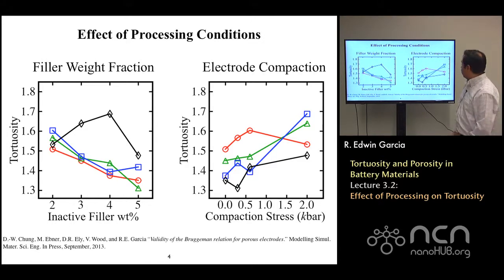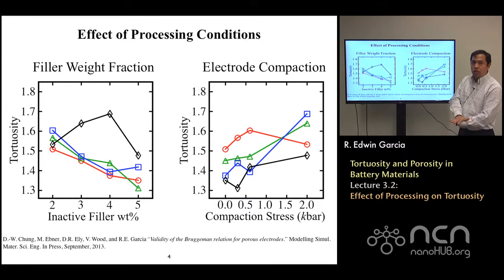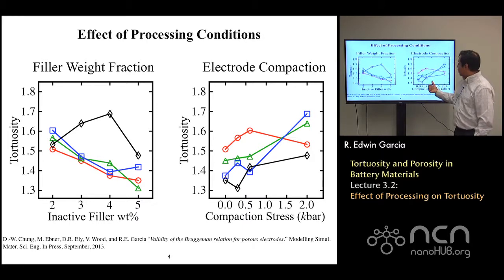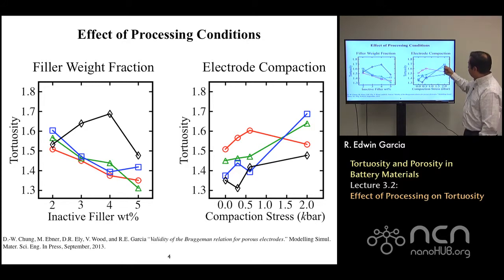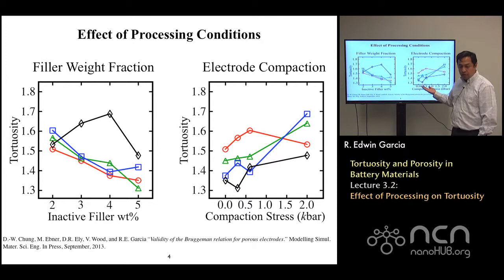If you see the same response as a function of compaction for a fixed amount of filler, they roughly follow the same trend. As you compact your electrode, particles get closer together, making the diffusion transport length become longer and longer. You can see the effect seems to be going from 1.3 to 1.7 — it seems relatively weak, but it certainly has some impact. And this effect does not include the effect of the underlying carbon black.